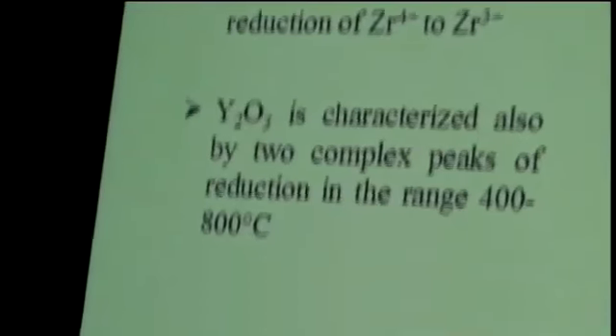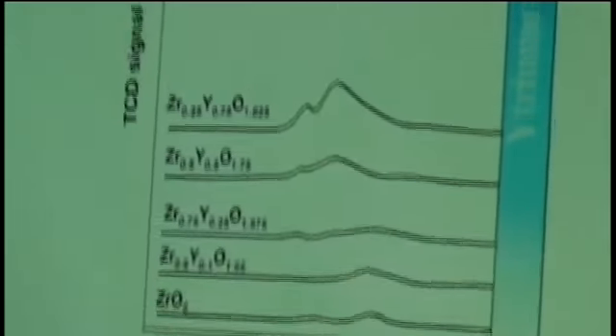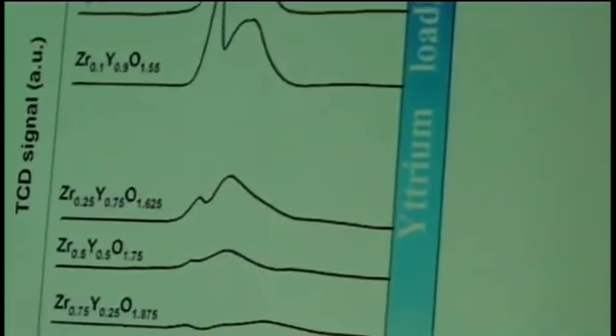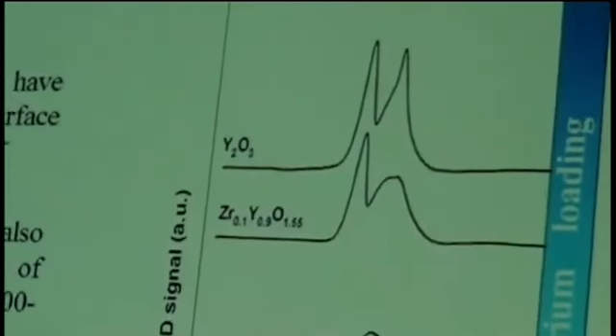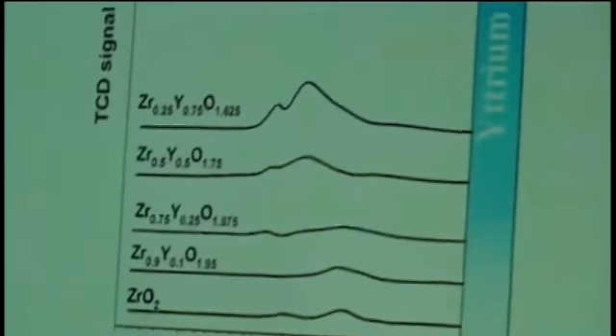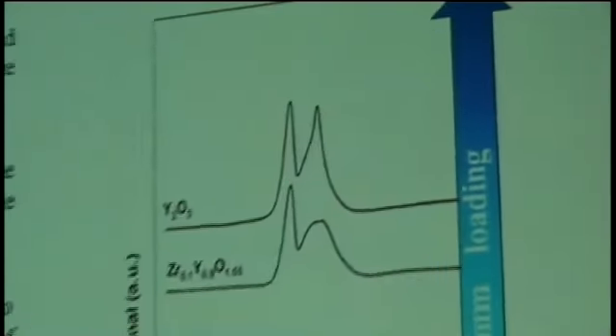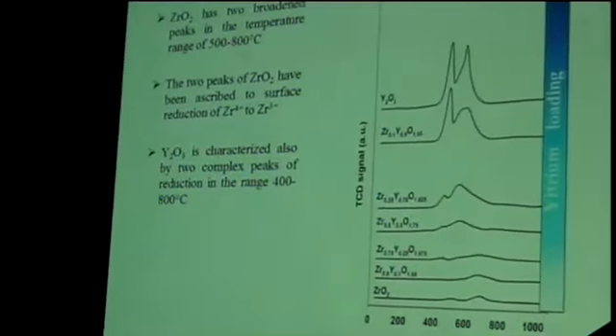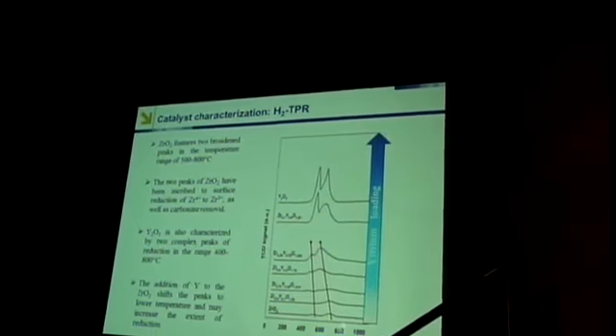The TPR profiles are very complicated. These are the catalysts without the platinum, so these are the supports. In the literature, researchers tend to assign these peaks in the 400 to 650 region to surface reduction. But really, these peaks are too large to just be surface reduction. You don't usually get a very high degree of reduction of these kinds of materials. If you do a DRIFTS study, where you look at the decomposition or the activation of the catalyst, you'll see there's significant carbonate removal from the surface. So these peaks are due to not only surface reduction, but also carbonate removal. There is a shift in the peaks to lower temperature as we increase the yttrium doping.